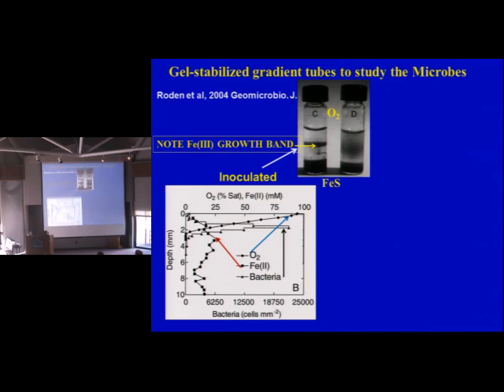So here's what a gel would look like. Typically you use FeS as your iron source, and that's usually at the bottom. And then you have your medium in here. This is an iron-3 growth band in this case. You have oxygen above, iron below. In this case, you'll see the oxygen basically going to 0 at about 2 millimeters. The iron is overlapping. It goes pretty much to 0 at the surface. All right? And right here is where the bacteria are, and that's where the band is.